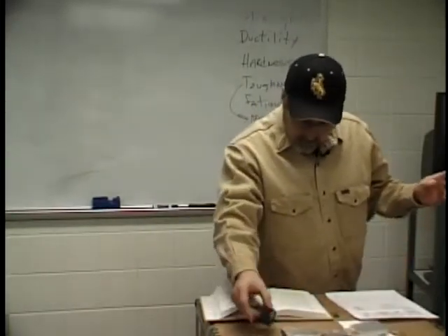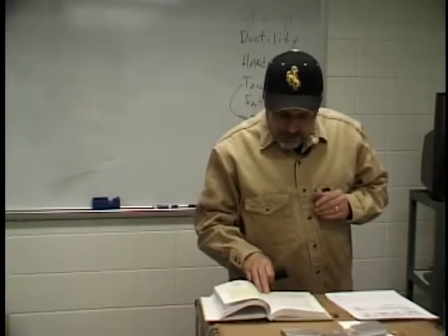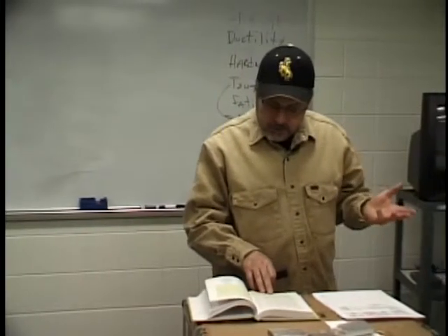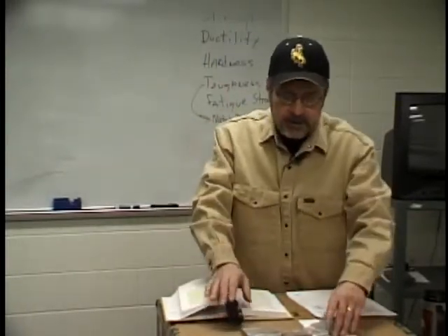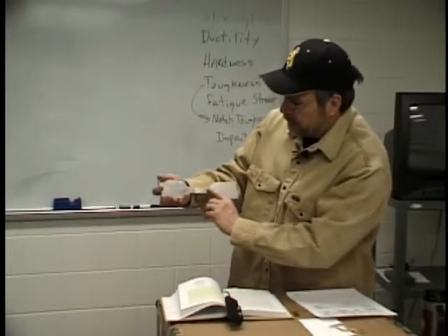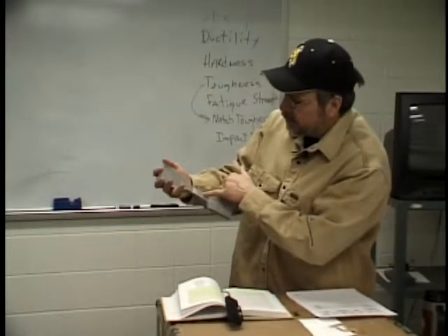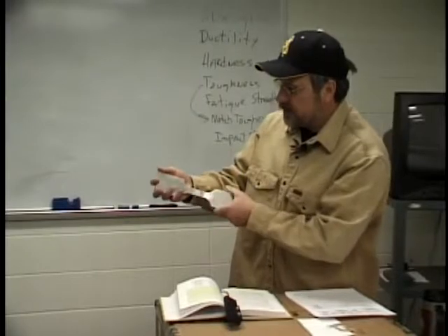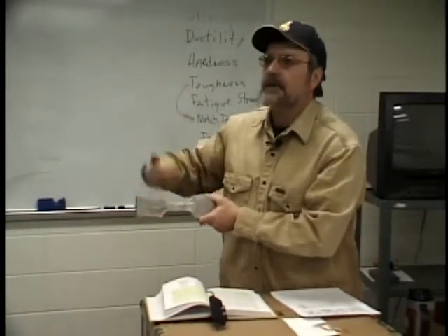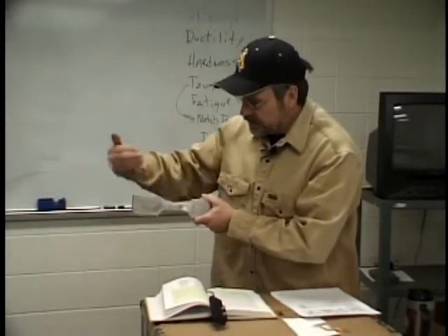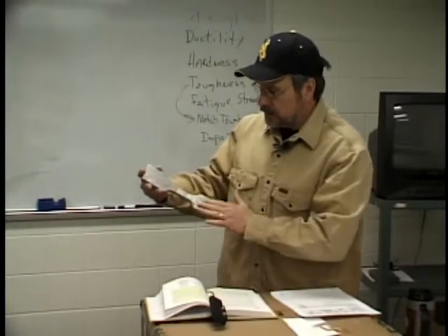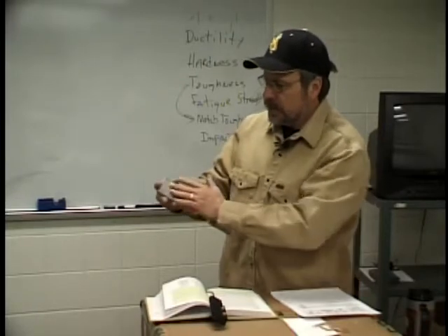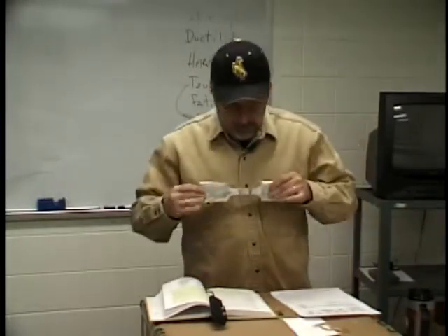So also highlight where it says fractures due to fatigue are often the result of sharp corners, scratches on the surface of the metal, or tool marks. So even something as simple as that can lead to a failure. On this particular specimen, this was machined down, but they didn't quite get it all the way down. So over time, if this was subjected to a continuous repetitive vibration or some kind of stress, it could fail at this point because surface notches do have a direct effect on its fatigue strength.